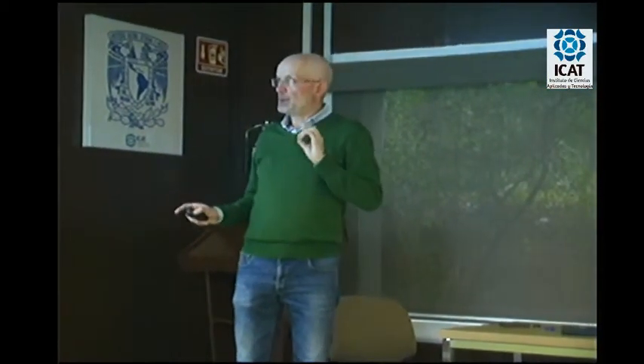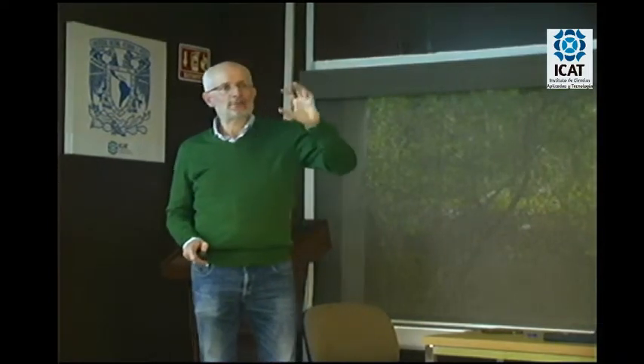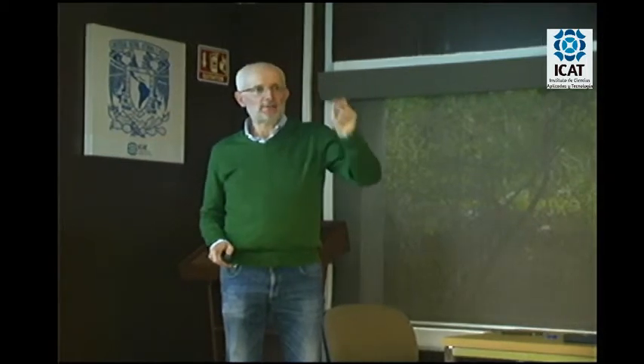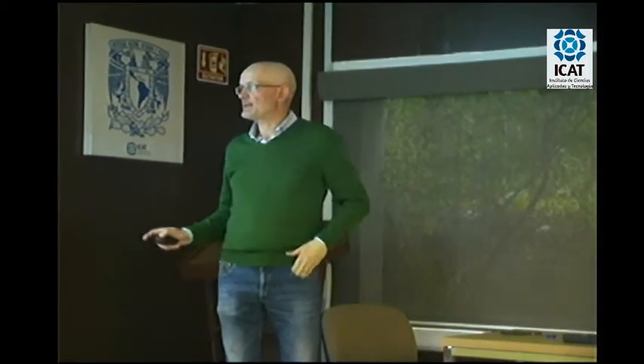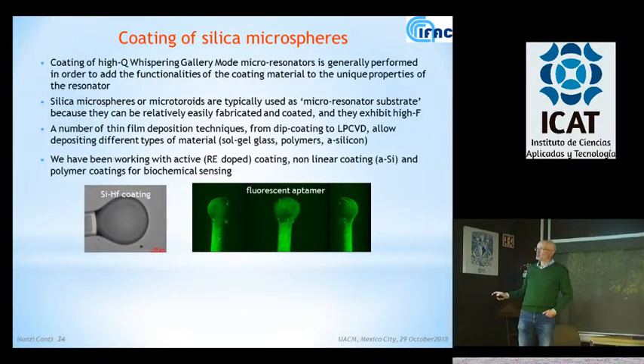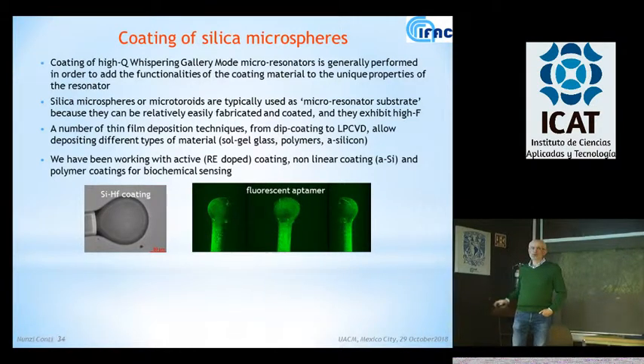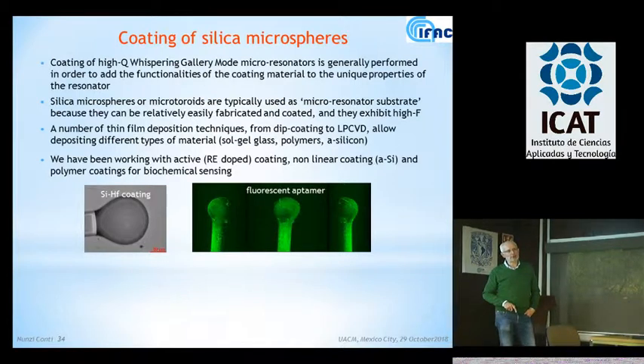Of course. And the other thing was, when you coated the sphere with metal and approached the fiber, did you excite any gap surface plasmon polaritons there or not? Okay, in this case, we are always working with dielectric coatings. We have also been investigating some features, but so far you spoil a lot. We were putting some silver ions in through some technique, but the Q factor is spoiled too much so far. What we have been working with is active sol-gel, like silica-hafnia doped with erbium, and polymers with some dye or fluorescent aptamer, for sensing, and amorphous silicon for nonlinear effects. So not with metals.